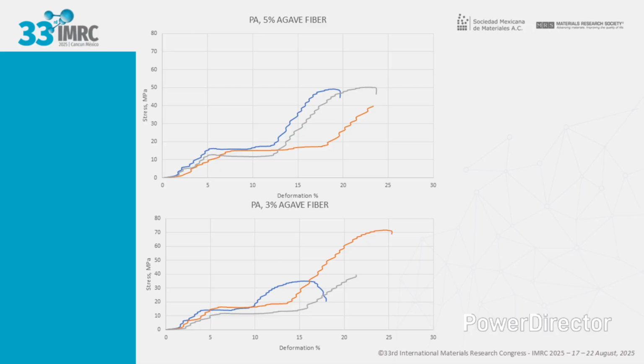This variability may be associated with inhomogeneous fiber distribution, the presence of agglomerates, or differences in the interfacial adhesion between the matrix and reinforcement. The higher stress case suggests that, when the fiber is properly dispersed and oriented, it can transfer load more efficiently, significantly increasing strength. Therefore, it can be concluded that at low concentrations, 3%, the reinforcement is more sensitive to fiber distribution and orientation. Results with high potential performance are obtained, but with lower reproducibility, indicating the need to optimize processing.